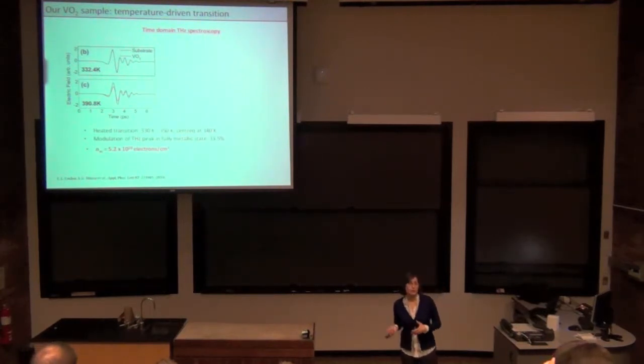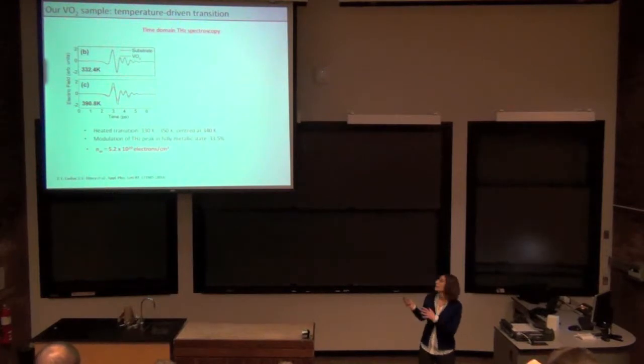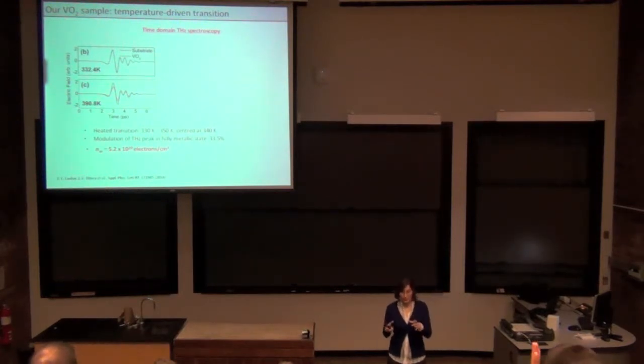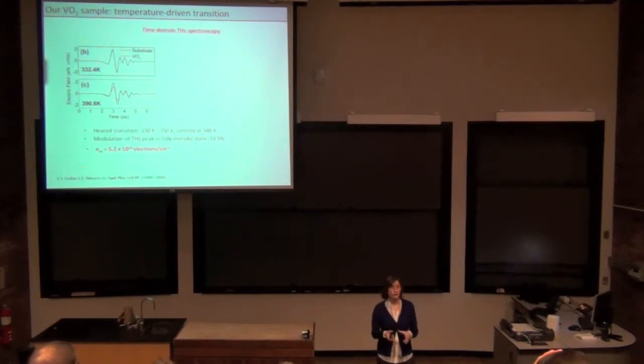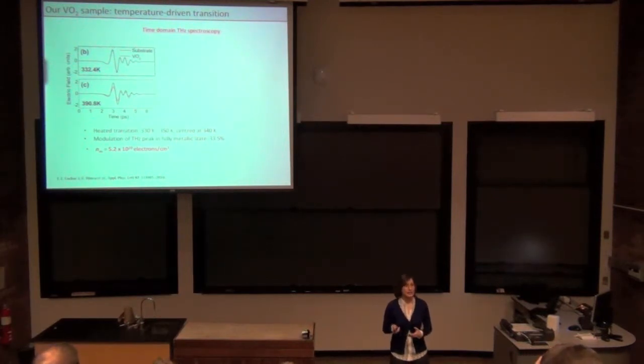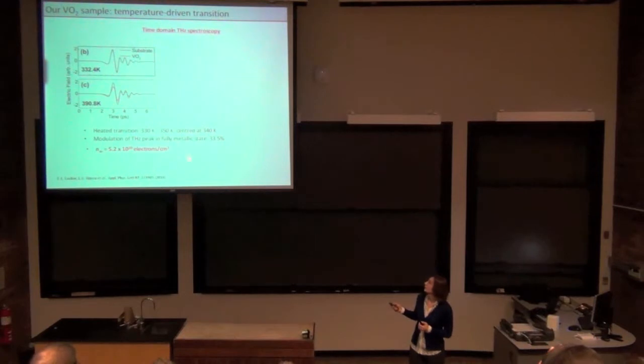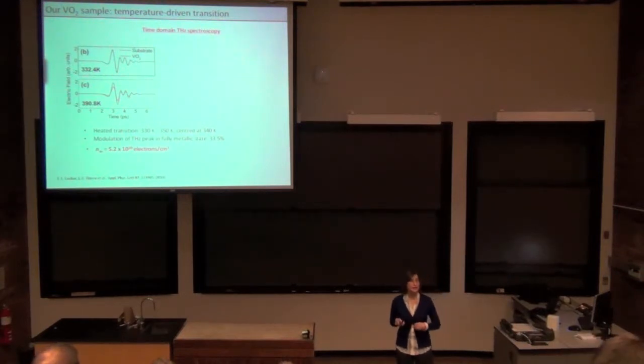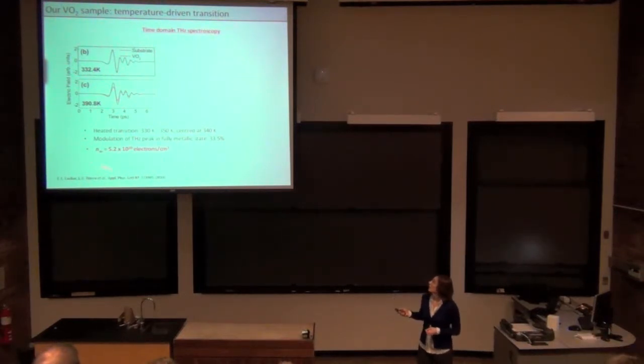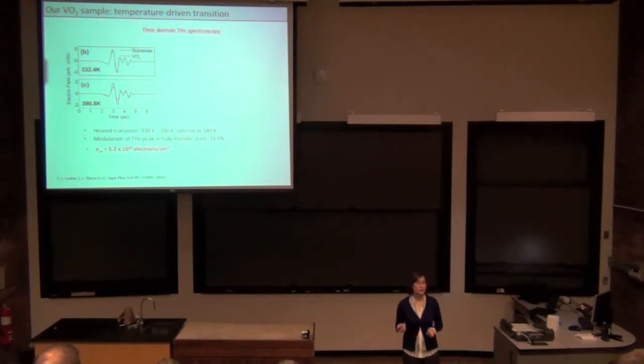As I showed you before in the silicon nanocrystal case, and I'm not going to show this, it's not so important to look at those spectra, but from the spectra we can fit and get the carrier density. This is an important number that helped us later analyze the photoinduced transition. We know that in the fully metallic, fully switched state, the carrier density is 5.2 × 10²⁰ electrons per centimeter cubed.